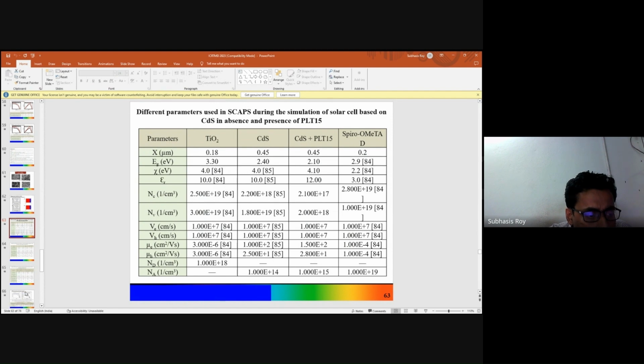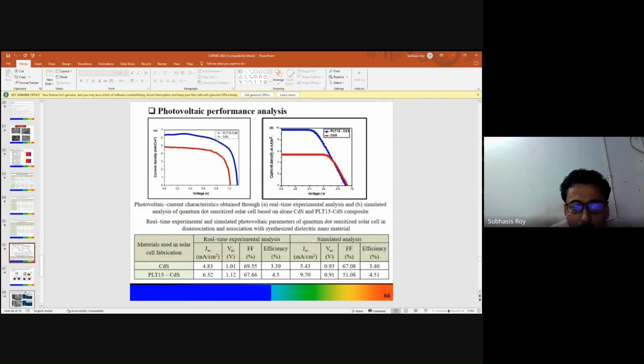And finally, we check the simulation study with the experimental study, and we match the simulation study with the experimental study, so that we can see whether the simulated result holds up in practice. We get around 5% error in the simulated value.